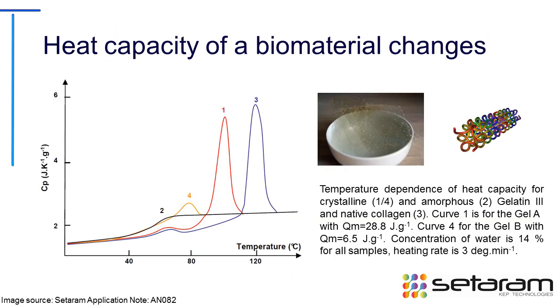So we're just going to look at some heat capacity values for some standard biomaterials, one of them being gelatin versus collagen. What's important here is that the first run right here is standard crystalline gelatin, and we can see that there's a dependence of heat capacity on temperature. We see a huge spike of the heat capacity compared to its annealed or amorphous polymer or amorphous gelatin. And that's why we need to measure these types of materials.